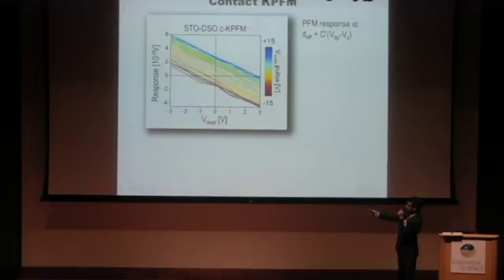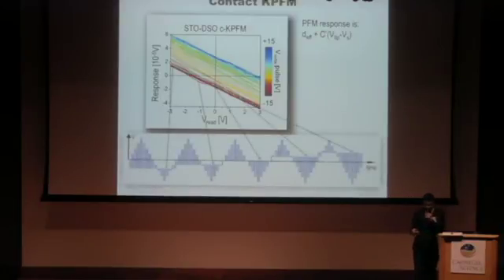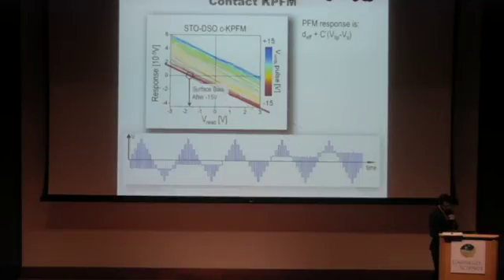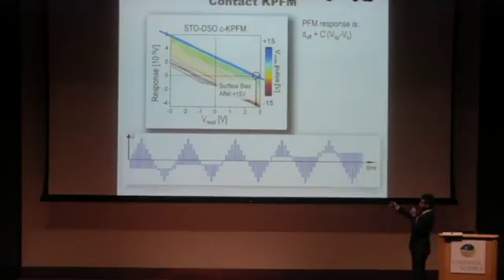This here, the x-axis, is the read voltage, or those offsets that I showed you before. Each one of these points comes from these offsets at a particular write voltage, which is given by the color. So if you go along this line, it tells you the surface potential after applying some voltage. In this case, after we apply minus 15 volts, of course this red line here, you can read the surface bias, which is around minus 2.7 volts. Similarly, you can do that on the positive side. After applying plus 15 volts, you see that the surface bias is something like 2.8 volts.